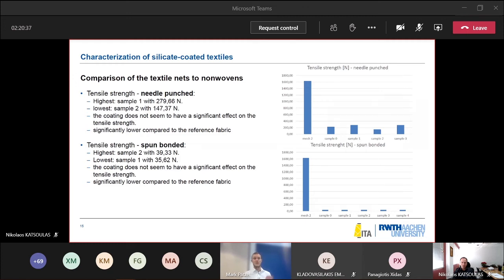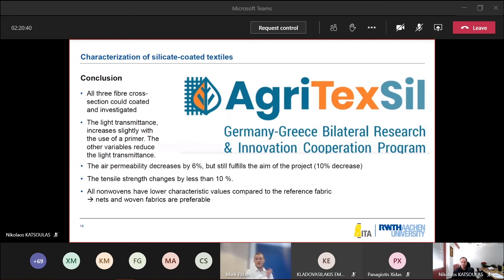So let me conclude. All three fiber cross sections could be coated and investigated. The light transmittance increases slightly with the use of a primer, and the other variables reduce the light transmittance. The air permeability decreases by 6%, but still fulfills the aim of the project. And the tensile strength changes by coating by less than 10%. Regarding the non-wovens, all non-wovens have lower characteristic values compared to the reference fabric. So in the framework of this project, nets and woven fabrics are preferable to non-woven fabrics.